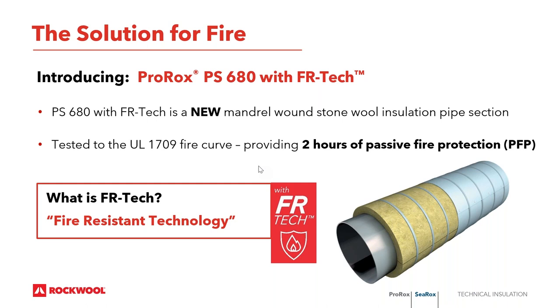FRTech incorporates an innovative fiber structure and chemistry to ensure mechanical and chemical stability during a fire. These are requirements that are critical for reliable performance. This product has been tested to the industry recognized UL 1709 fire curve, and it is providing up to 2 hours of passive fire protection. The UL 1709 is considered the industry standard most frequently specified for passive fire protection.